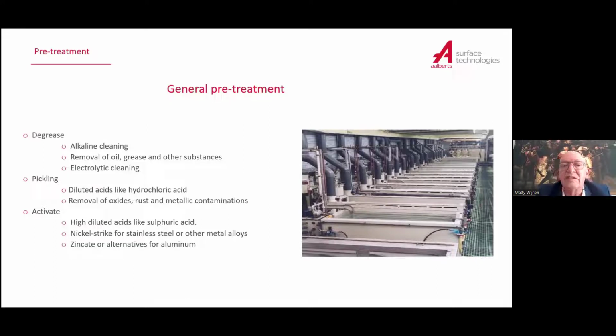After that, you have to activate them again. And quite easy, the normal steel metals, it's not difficult. You use a very diluted acid for that. But if you have to go to higher alloyed steels, like stainless steels or even high nickel alloys, you have to make special activation treatments, just like nickel strike or something like that.